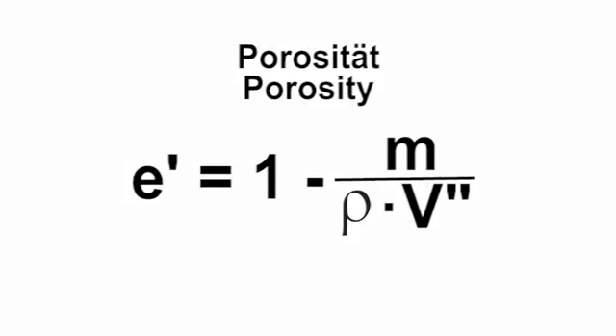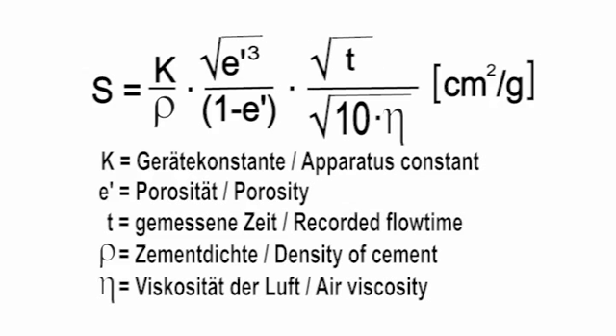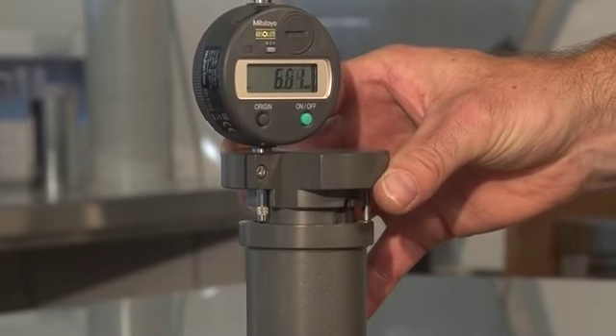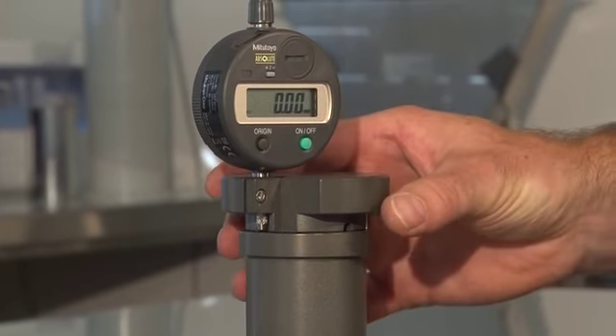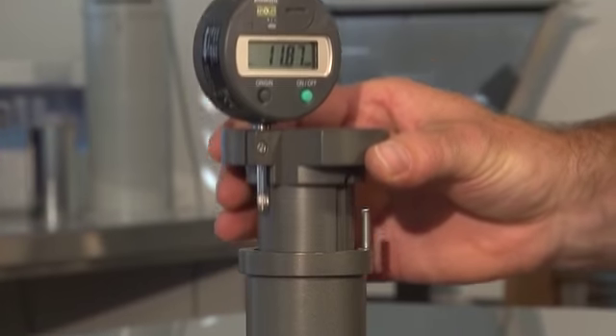The determination of the two flow times follows as usual. With the newly determined porosity, the mean value from the two flow times and the temperatures of the sample, the Blaine value can be calculated. All other regulations apply as usual. If a sample weight is too low and the plunger falls through, the cement bed must be recalculated and reproduced.